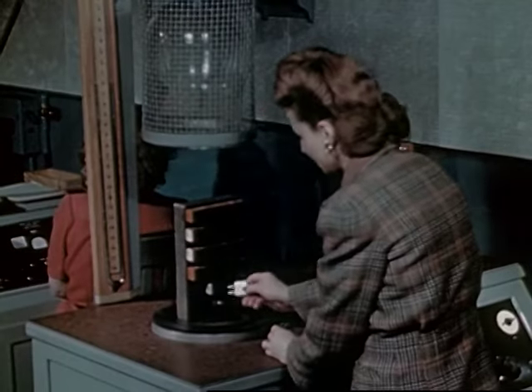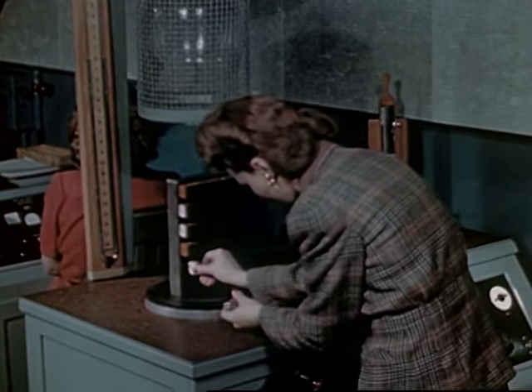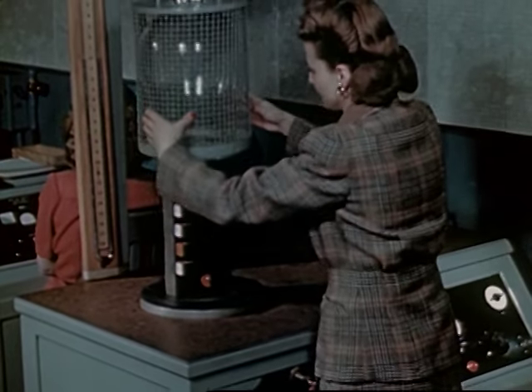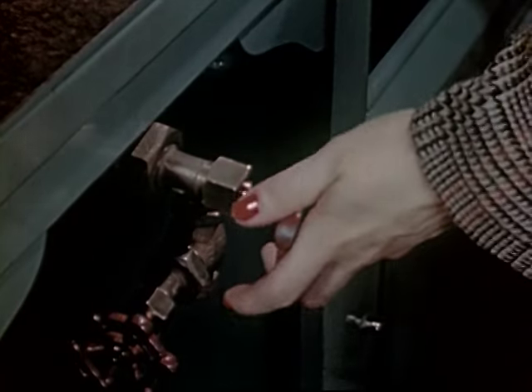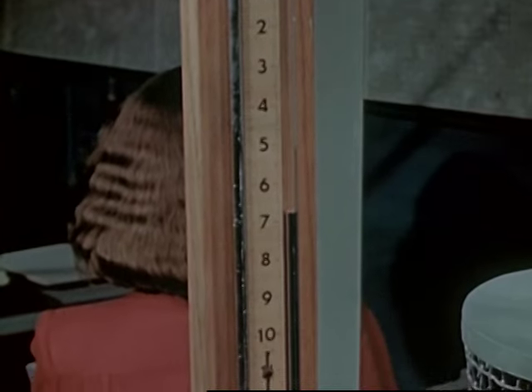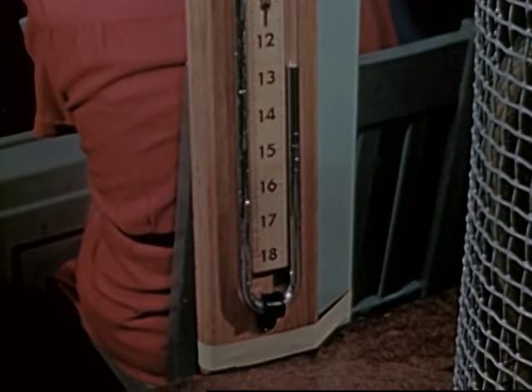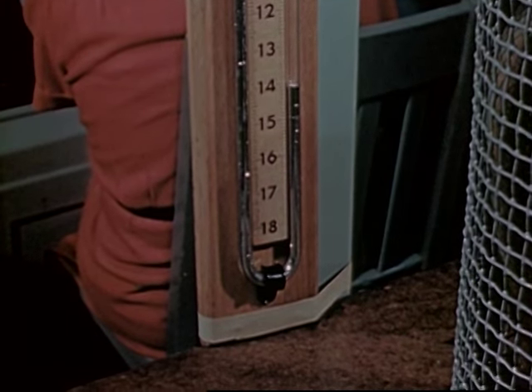At the completion of the temperature test, a final production test is made to see that the holder is tightly sealed against leakage. The crystals are plugged in groups of 60 into a rack, which is enclosed in a glass vacuum chamber covered with wire mesh for protection. The air is pumped out as shown by the changing level of the mercury manometer. A potential difference of more than 1,000 volts is placed across the electrodes. If the holder leaks, an ionization current registers on the dial.